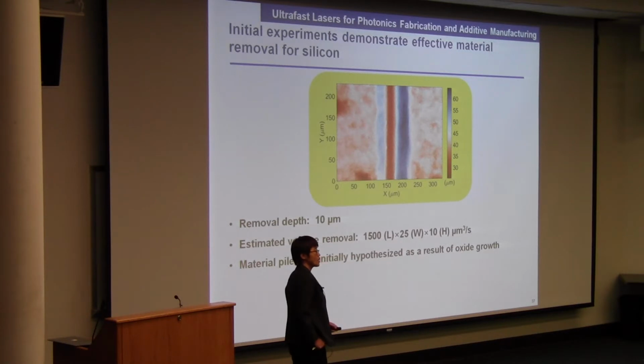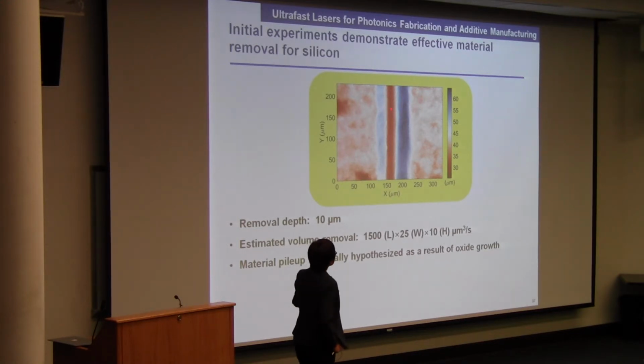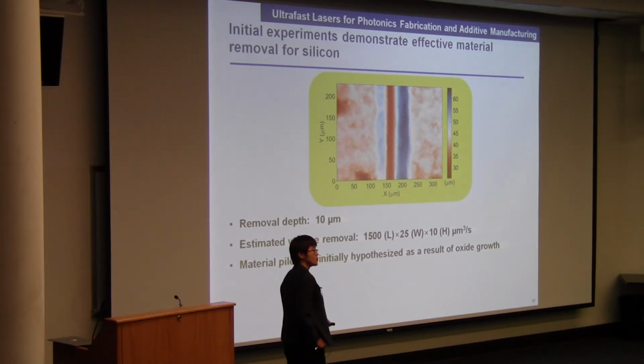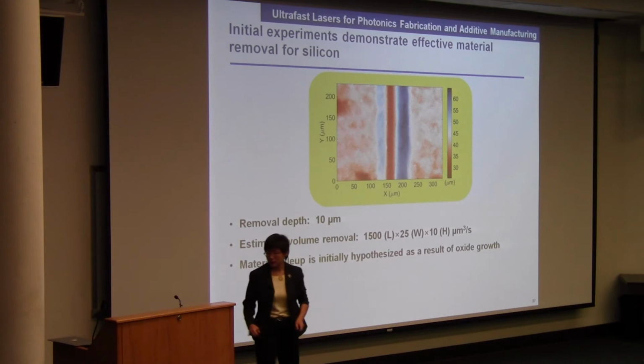And I showed this data to my collaborator at NASA Goddard, who works on lasers, and they do polishing for silicon. And he was amazed by the effectiveness of this laser ablation for silicon material. So we were happy with that, but we also see some unexpected effect. Rather than removing material, we see material pile up on the side of the ablation. So we wanted to understand what caused that and how to affect that.